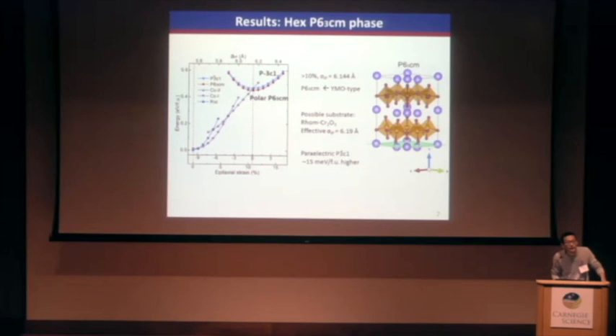And of course, those occur closer to equilibrium lattice constants. But you may find some interesting magnetic analogies where you could learn about the energy magnetism relationships and see if they still hold for this interesting metastable ferrite. Okay, I think I can talk further with you. But I can let you know that since we are talking about bismuth ferrite, if we replace the ferrite with a manganite, the phase diagram looks quite similar. It can also be stabilized in manganite, the two phases.